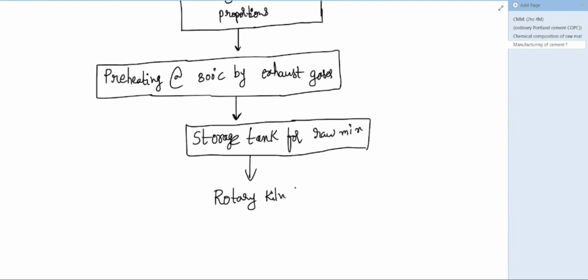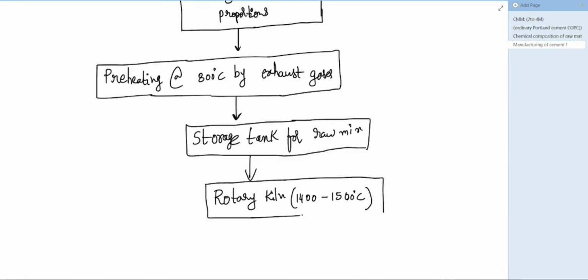Rotary kiln, where the temperature is maintained around 1400 to 1500 degrees centigrade. Now you see, in this case, the temperature is 100 to 200 degrees centigrade less because of the dry mix. Hence, the kilns required in the dry process are less in height. Even the cost of fuel is also less because less temperature is required, around 100 to 200 degrees centigrade less. As fuel, we add either coal, oil, or natural gas.